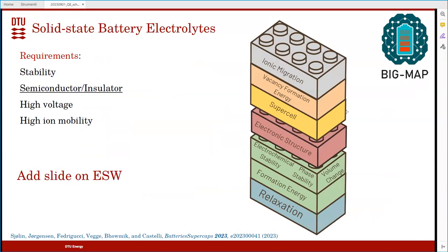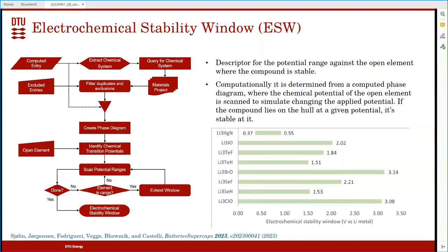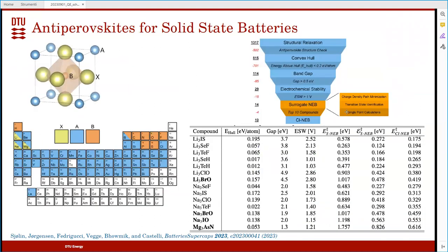We took exactly this, and then we had only one extra block. And then we took about 6,000 different antiperovskite materials. In a normal perovskite, you have the octahedra made of oxygen, so negative, and the two cations are positive. In this case, you swap. So the octahedra is positively charged, and the A and B cations are negative. Because of that, in principle, you could have a higher conductivity and higher capacity, because now you have three lithiums instead of only one, but you pay a bit of stability.